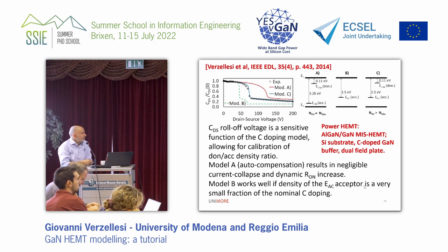As you can see here, we found that the drain-to-source capacitance roll-off voltage at increasing drain-source voltage was a sensitive function of the carbon doping model. These are Infineon devices, taken from, I forgot to put the paper here. Oh no, here, this paper.